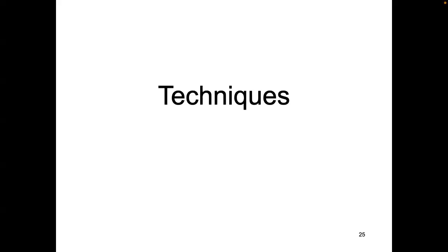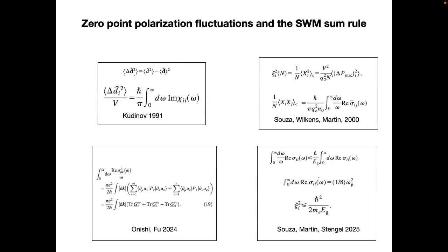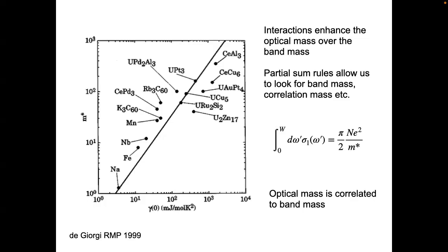So the question was whether the mass you get from optics is similar to the mass from heat capacity, and that was the plot that I showed you. They either are or are not the same, depending upon how much you worry about log-log plots and scatter. Let me go back. There, right? So the horizontal axis is the heat capacity, and the vertical axis is the mass extracted from optics, essentially the integral of something which looks like the Drude response. This is plotted on a log scale, it's 3 orders of magnitude. That's pretty good.